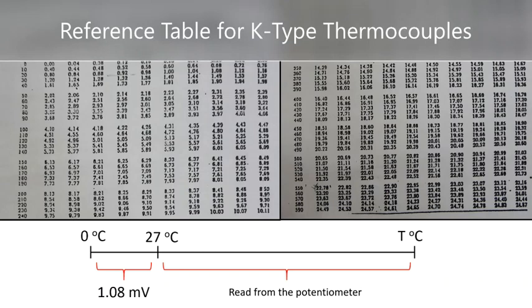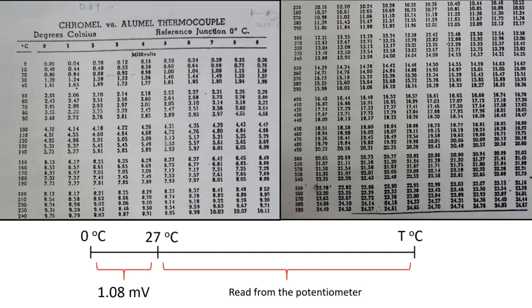This measurement is important because the reference table for k-type thermocouple is generated when the cold junction was at 0 celsius degrees which can be kept constant using ice water mixture. In order to find the correct temperature value we need to make a correction procedure because the cold junction in our case is at room temperature not at 0 celsius.